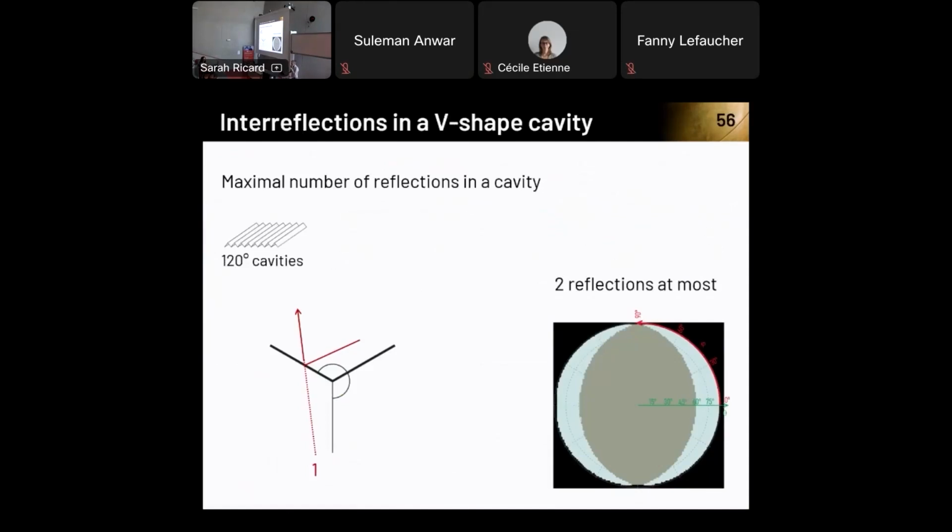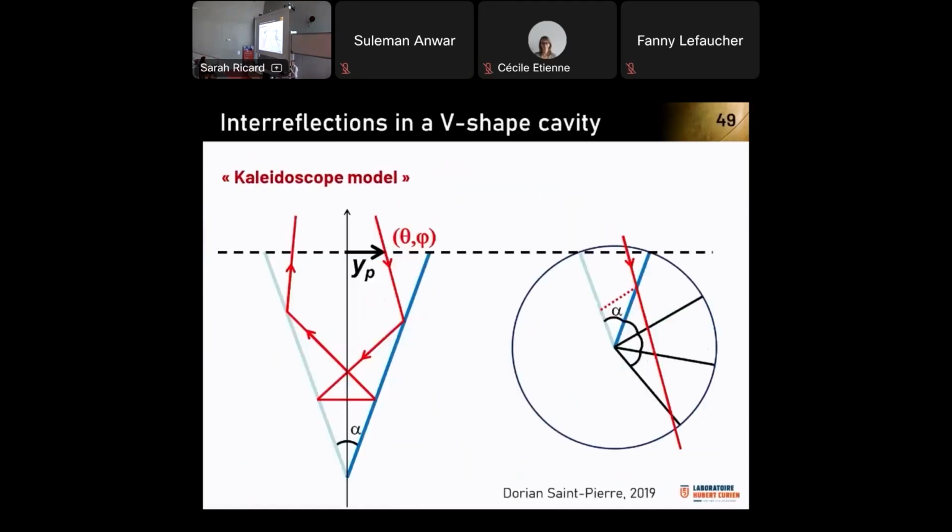because yes, what happens? Here it is very easy when we have mirrors, and when it is not a mirror, it means that the first rays start to be scattered, and then more scattered and more scattered. Actually, the advantage of that is that it is similar to what we call a two-flux model. We have an analytical model with formulas. So in terms of computation, you can have all the angular configuration in seconds or at most a minute.